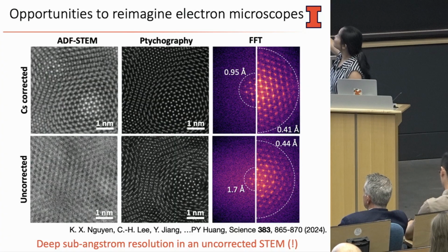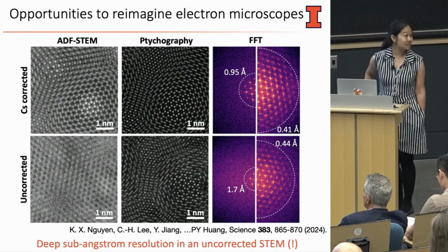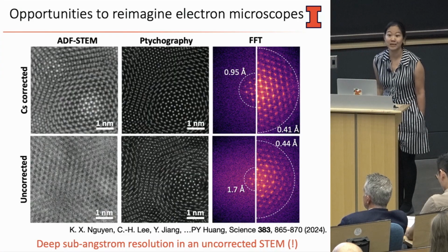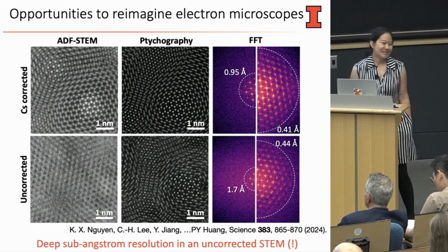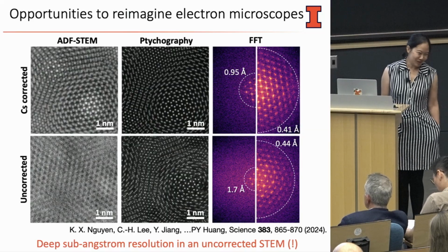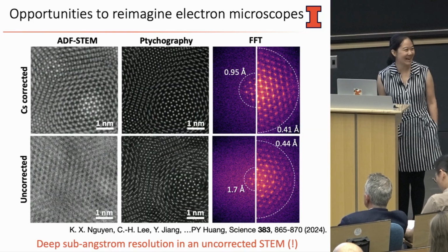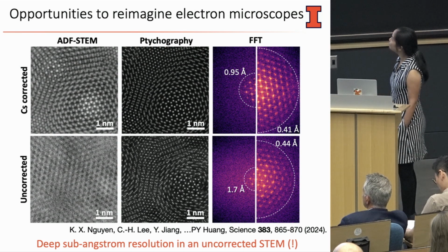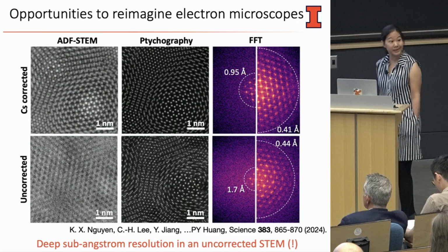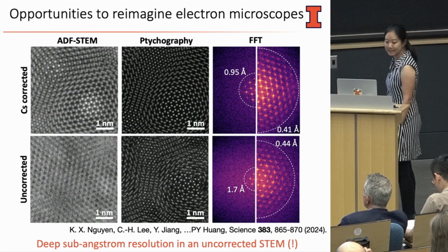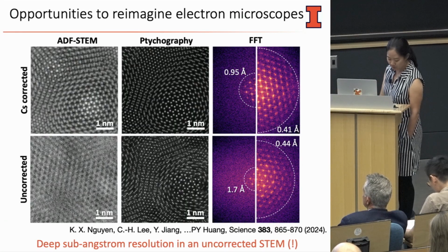And then with ptychography, we hit 0.4 angstroms, again, just as good as the best aberration-corrected microscopes out there. This is really important because not everyone has $8 million in their dresser drawer to go and buy that best microscope in the world. But using ptychography, you can make a medium range, much more affordable and accessible microscope perform like a great one.